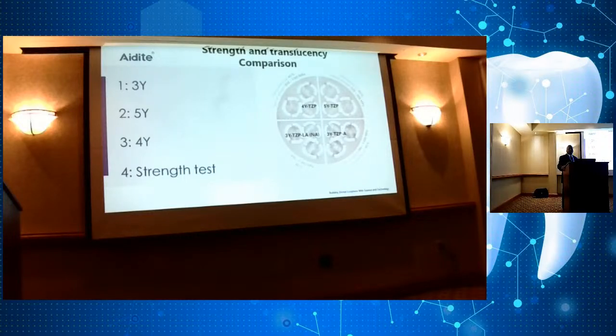Veneers and porcelain butt margins used to always give me trouble, but it's doable. With a material like 3D Pro that my friend is using, it has beautiful translucency. You can adjust the translucency, and it has really nice chroma. If you use your CAM software, I can mill like a 0.2 reduction on the margin, and because of the way the material is composed, it's very high density and also has 1050 MPa.